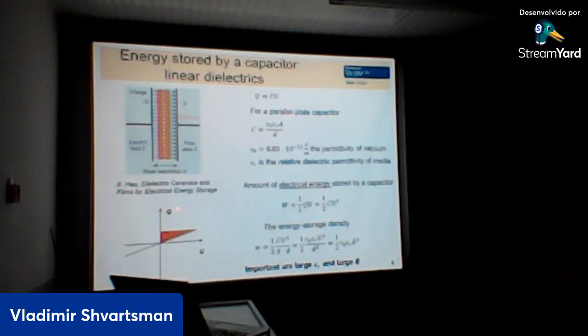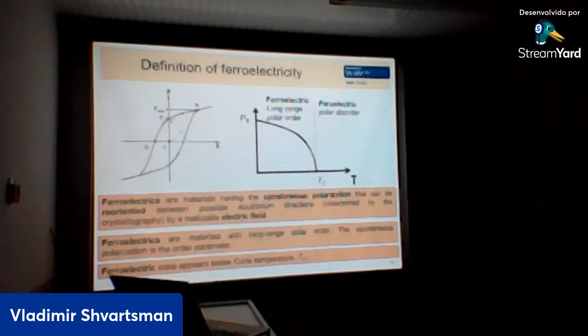This is illustrated here, with charge on the y-axis and applied voltage on the x-axis. The stored energy is given by the area between the linear charge-voltage dependence and the axis of charges. Of course, as is clear from this equation, when we have a dielectric with a large dielectric permittivity and we can apply a large electric field, we can store more energy. Typically, linear dielectrics have a very small relative dielectric permittivity, around 10. Therefore, it's interesting to go to other materials, the ferroelectric materials, which have much larger dielectric permittivity. It can be 1,000, even 10,000.